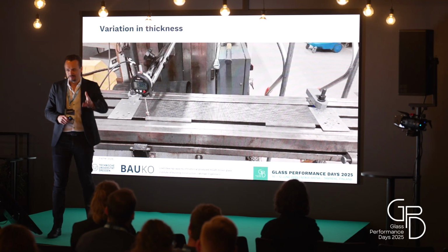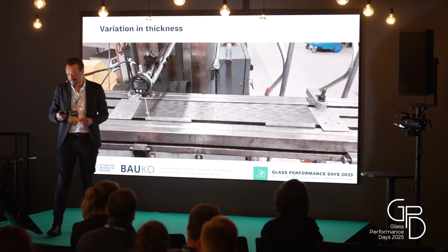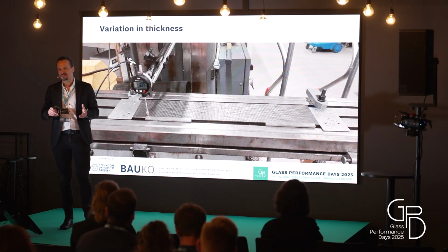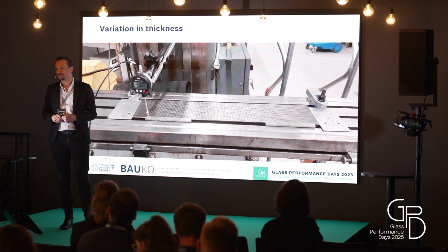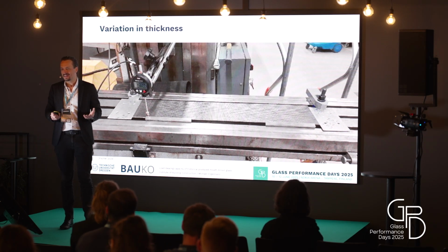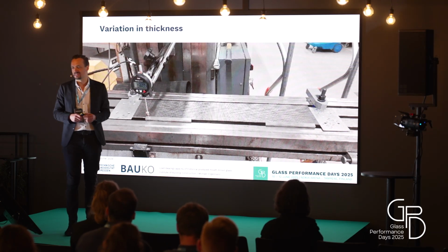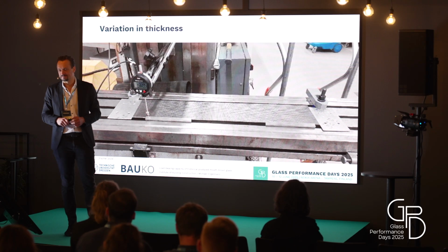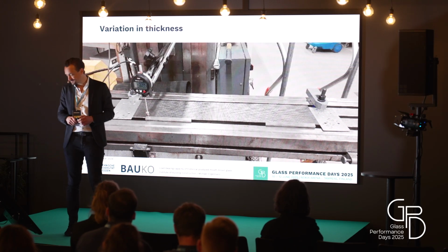One of my team members, so we prepared this perfectly. So we have 0.2 millimeters. And of course, you know, when you buy float glass, you will find actual thicknesses very close to the lower limit of the tolerable thickness.